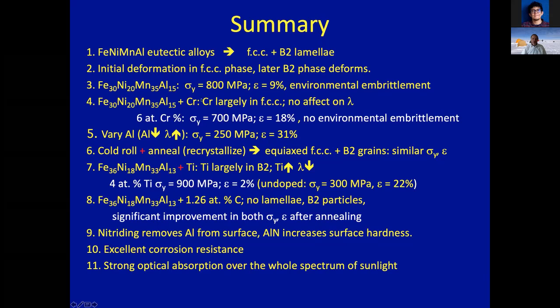So you can add chromium to it. Chromium largely goes into the FCC phase and doesn't really change the microstructure very much. It lowers the yield strength, but roughly doubles the elongation to failure, and it overcomes this environmental embrittlement. We looked at varying the aluminum content, and as the aluminum content goes down, the lamellar spacing goes up, and so the yield strength goes down and the ductility goes up.